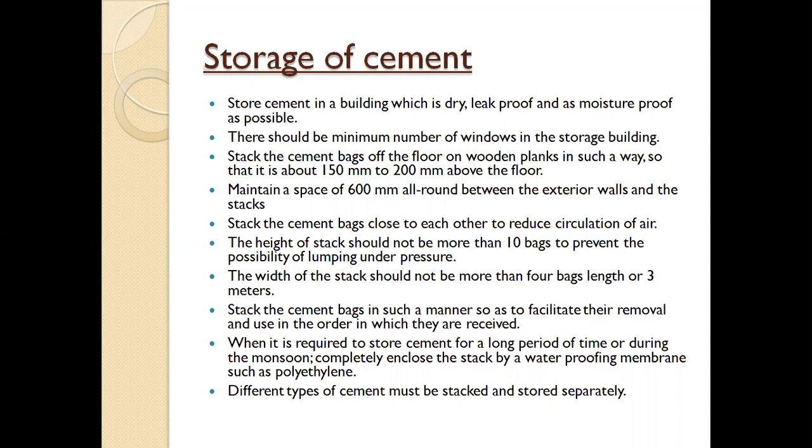Stack the cement bags close to each other to reduce the circulation of air. So the cement bags or the stacks should be close to each other to avoid the circulation of air. The height of a stack should not be more than 10 bags to prevent the possibility of lumping under pressure. So the height of a stack should be a maximum of 10 bags.